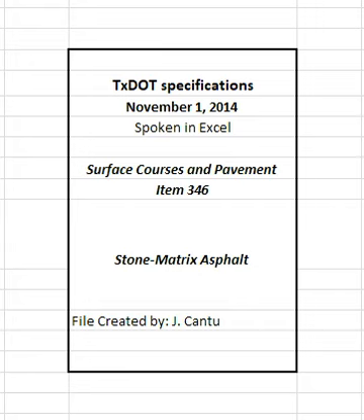2.4.2 Asphalt rubber, AR, binder. When SMAR is specified, provide AR binder that meets the Type I or Type II requirements of section 300.2.9, asphalt rubber binders, unless otherwise shown on the plans. Use at least 15% by weight of crumb rubber modifier, CRM, that meets the grade B or grade C requirements of section 300.2.7, crumb rubber modifier, unless otherwise shown on the plans.